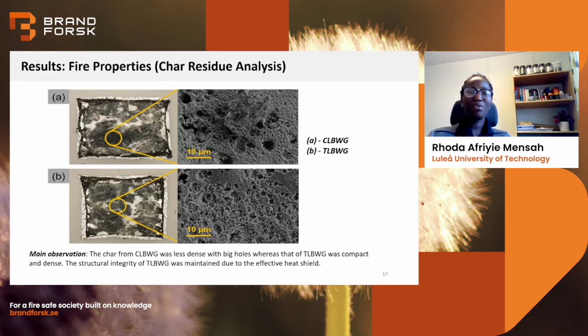We observed the char residue from the cone calorimeter of the chemically doped and the thermally doped samples in the scanning electron microscope. And the micrographs shown as A and B, from these images, we see that the CLBWG sample has a less dense char with big holes in them. And then the TLBWG, that's a thermally doped sample, has a very compact and dense char with small holes in them. So from here, we can say that the structural integrity of the thermally doped sample was preserved during the burning process.